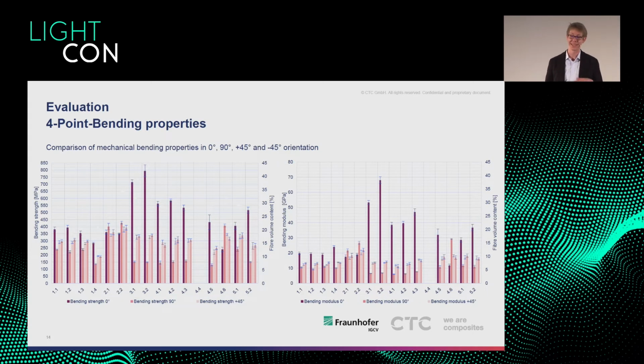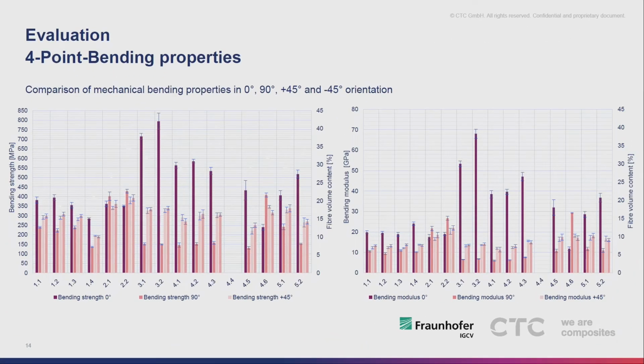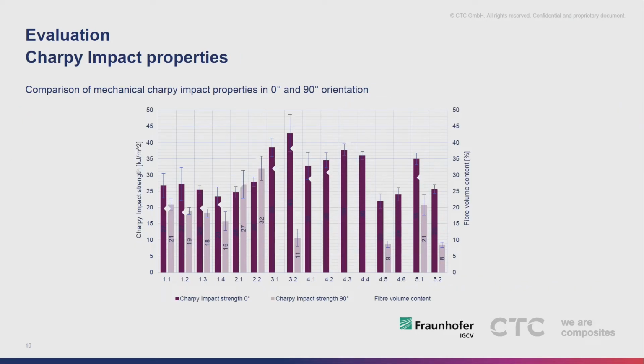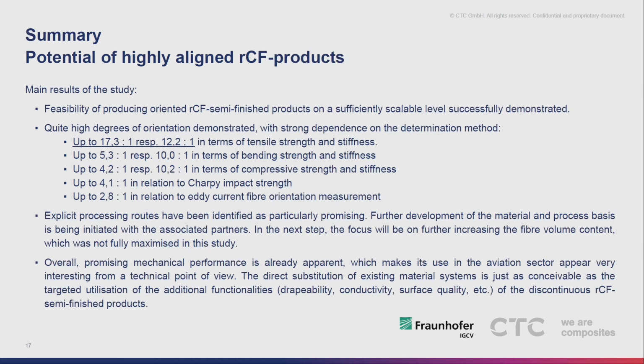And as I said, I'm not going to read all this. I will leave this data with you, and I'm happy to answer any question about that. But those values are confirmed for tensile strength, for bending strength, for compression strength, and for Charpy impact properties. So we very, very clearly have a best and most favorite candidate for highly aligned carded textiles or highly aligned staple fiber yarns. And just to clearly point that out, these preferred technologies are based on yarns, high thermoplastic content, and most likely to be used in a thermoplastic application.